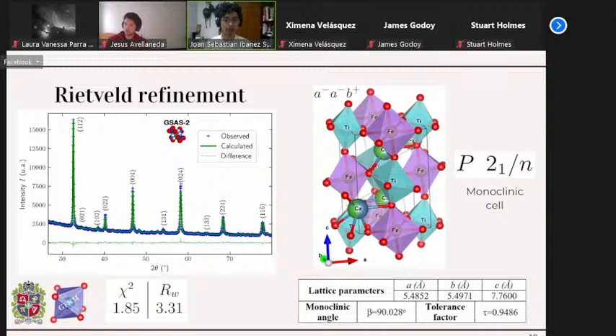We found that we had a chi-squared of 1.85 and a weighted residual of 3.31. In particular, we found the lattice parameters that you can see at the bottom of the screen. And we found that the space group corresponding to our sample was actually a monoclinic set, the P21/n, which is like a screw axis, if I'm not mistaken. Yep. We found, you can see in the image, the different octahedra,